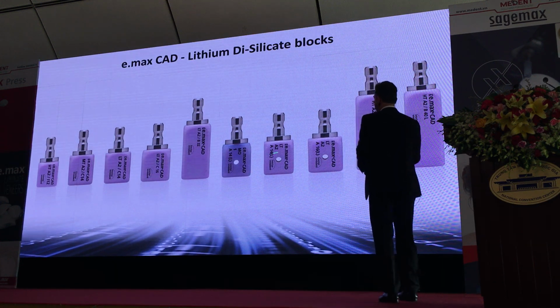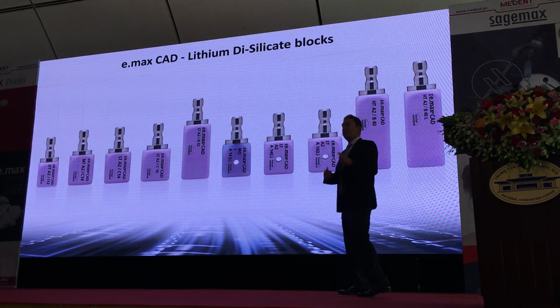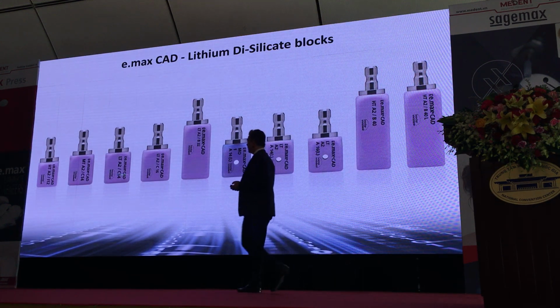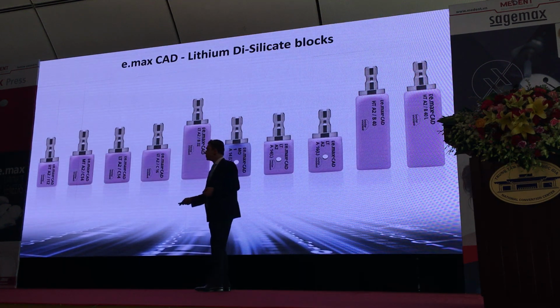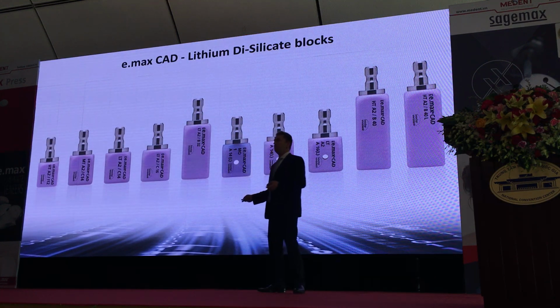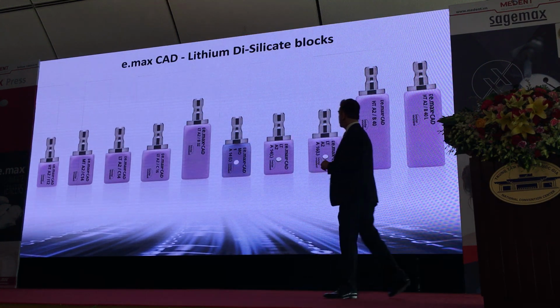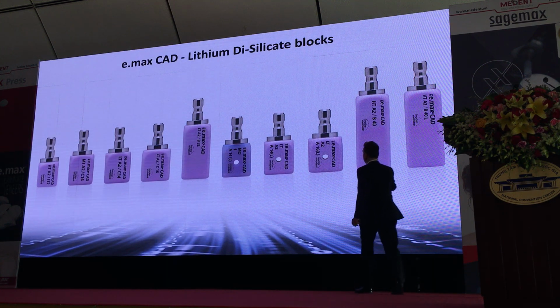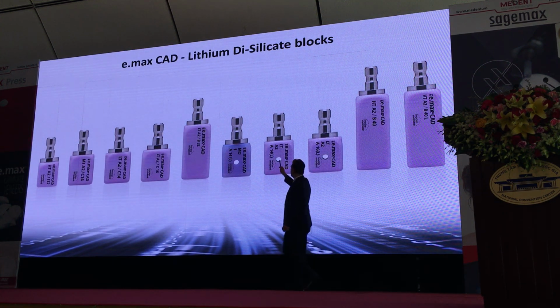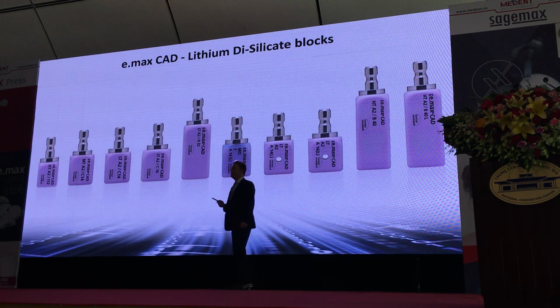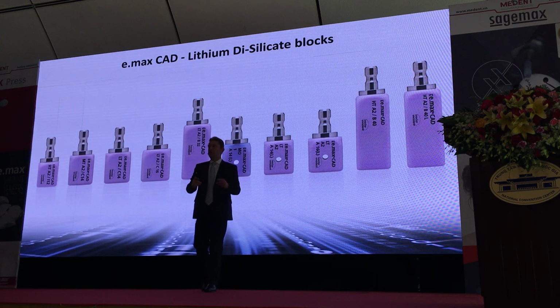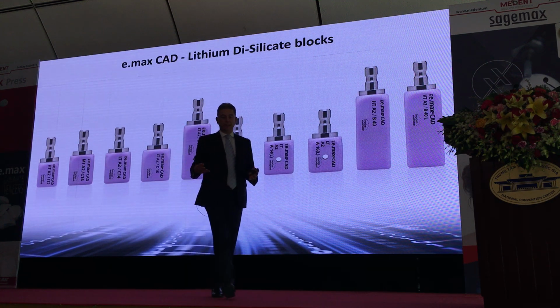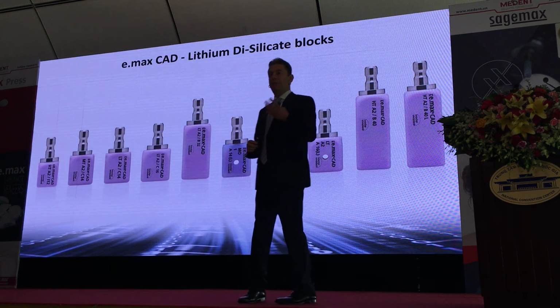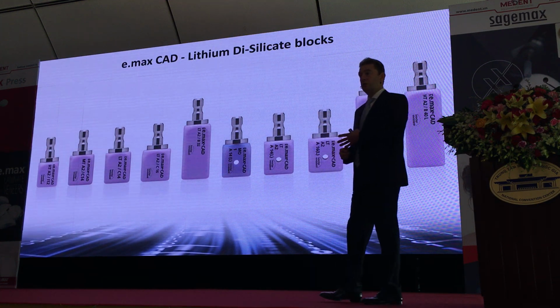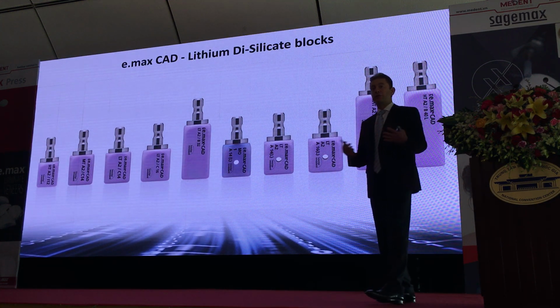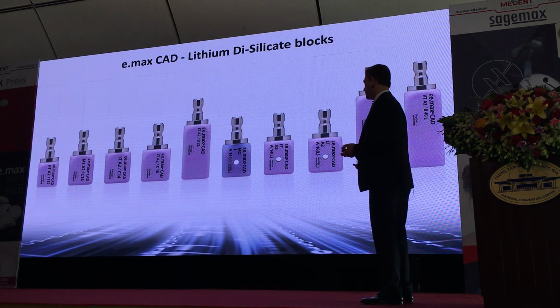So you can see when you look at the CAD/CAM blocks, we can do a lot of indications, right? So here we can do inlays, onlays, and crowns. With this block, we can do bridges, 3-unit bridges out of emax. And we also can do, which is very interesting, you can see those blocks with a hole can be combined with a titanium base. So now we can do an implant restoration, like an abutment or an abutment crown. Because the material is strong enough that we can place it onto an implant.